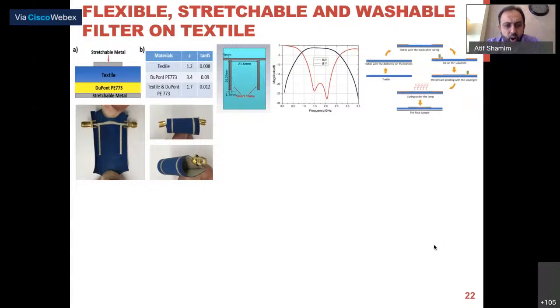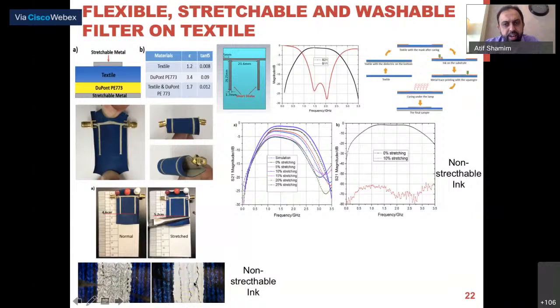As you could see, the non-stretchable ink got cracked. As soon as we stretched it, it got cracks and it would not work. So this is the graph on the right: you see that it works and then it doesn't work. Whereas the stretchable ink would develop a little bit of cracks at 30% stretching, but as soon as you release it, they fill up again. So it was still working up to 25 to 30% stretching, which is typical for a stretchable textile.